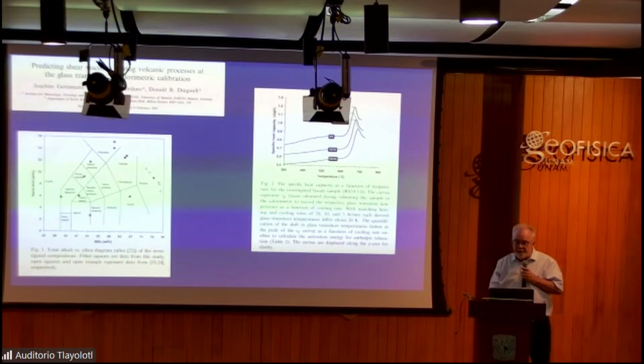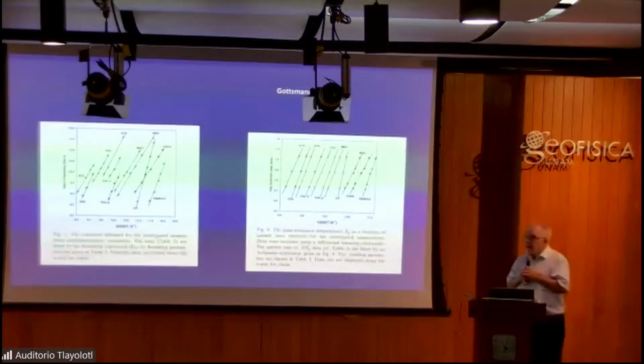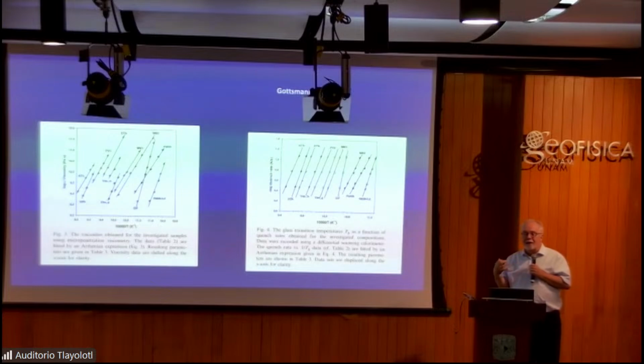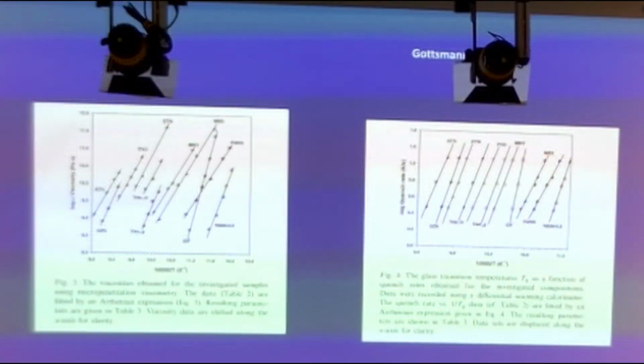And it's very valuable because where it occurs is directly related to the viscosity. Because the viscosity is the inverse of the diffusivities in the liquid. And the diffusivities are what controls relaxation of structure and movement of atoms. It's what wakes up when you cross the glass transition.